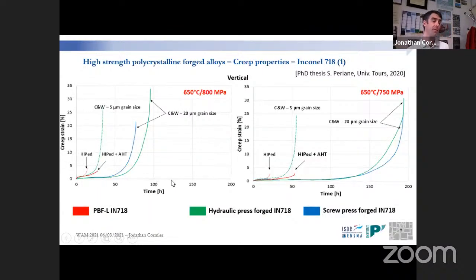If we move now to creep properties, we have been testing also creep properties at 650 C, 800 MPa, 750 MPa, same time scale here, in which we compare the powder bed fusion 718, so the red curves here, and two types of forging, hydraulic pressed forged 718 and screw pressed forged 718, the processes which are used for the processing of HP discs and LP rings for aero engines. What we can see in both cases is that the curves are pretty much the same in terms of primary and secondary creep stage, or up to 1 to 2% creep strain. Still, there is a very pronounced lack of ductility, which prevents the alloy from being used in that state for such kind of high strength, high integrity components.